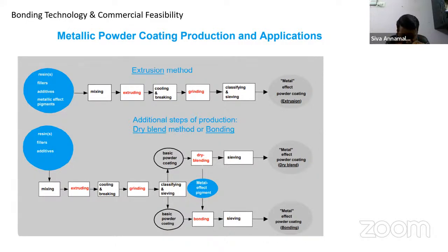And the third one, you cannot add more dosage of aluminum or any other metallic pigments, because once your metallic dosage crosses more than 3% in the final formulation, then your powder spitting is going to be higher. Chances for powder separation, gun choking, and gun spitting are very high. Sometimes spitting means when you spray, it looks like everything is fine, running well. Suddenly a bunch of powder comes and deposits over your object. It is like a spit. That's called gun spitting. So this will create a problem.